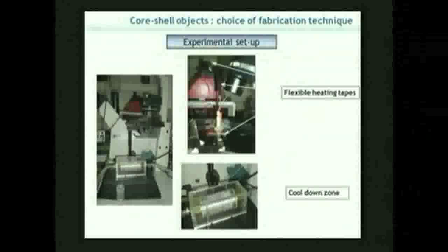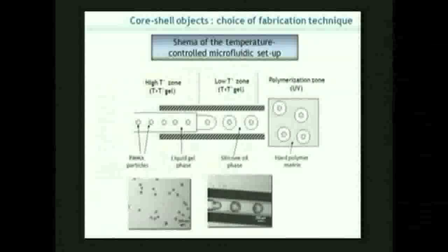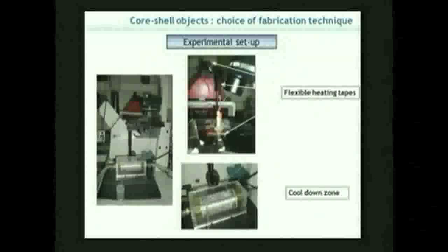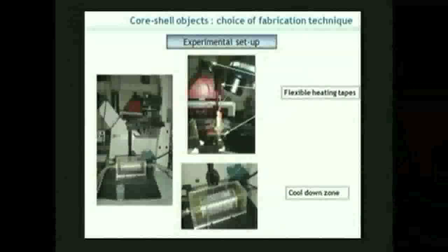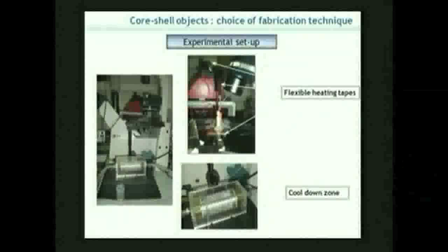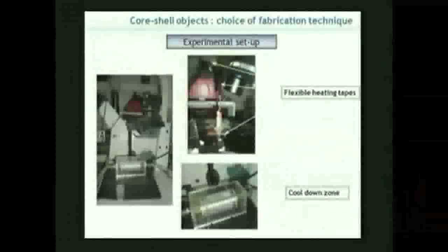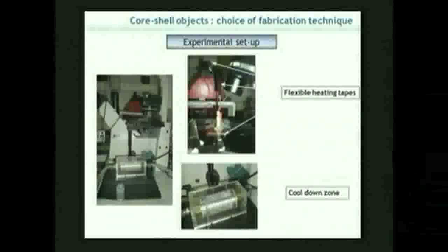Well, there's nothing really to comment on that. We do that under a microscope because the particles, you see, are about 100 microns, so you cannot see it only with your eyes. You need to use a microscope. And okay, so this is a picture of the chip, and here you need to have some heating tapes just to maintain the temperature at the right value. And you have also some apparatus here. This red thing here is what we call a syringe pusher, okay, that will apply a given flow to the fluid inside the capillary tubes. Okay, and after that you have a cool down zone. Here you have the tube that you roll over some piece of metal that is maintained at a low temperature, just to decrease the temperature to make the gel phase.